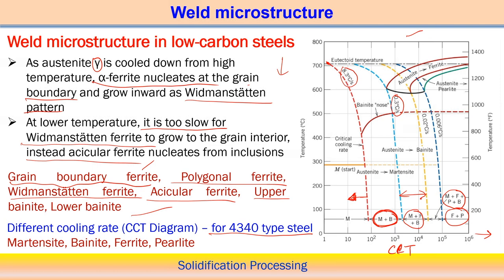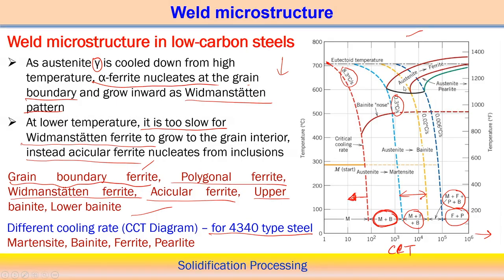So I mean to say that in this case, we can understand the effect of the cooling rate. At a very low cooling rate, we get the mixture of ferrite plus pearlite, but gradually we can see that at a very high cooling rate, we are getting the martensitic structure. In between cooling rates, we get a mixture of martensite plus bainite, or a mixture of bainite, martensite, ferrite, pearlite, all these kinds of structure depending upon the rate of cooling. So this is an example, and different alloy steels have a similar kind of diagram. If we follow this diagram, we will get all the information on what kind of cooling rate we should follow, such that we will be able to get one particular structure. So that is the influence of the cooling rate on the weld microstructure.